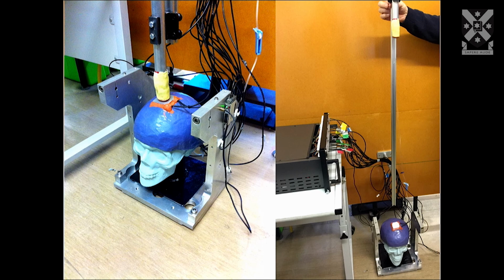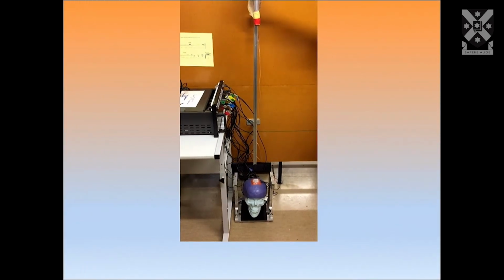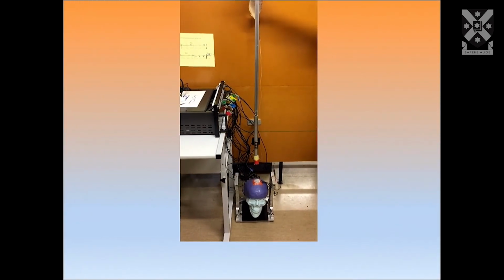So we took our kendo impact device, put it under here, and then adjusted the height until we were achieving the same level. So we knew that we had that the same. And then we put the head, and you see this line here. That was the cerebral spinal fluid going in to maintain the pressure. And we then started to impact the model.